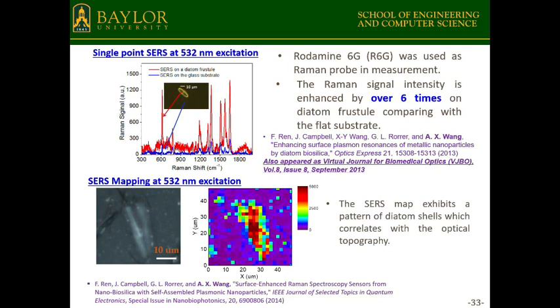And then we conducted SERS testing. So you can see the blue curve is the SERS from a nanoparticle on a flat glass substrate, and the red curve is the SERS signal from the diatom. The signal is greatly enhanced. In order to avoid random effects, we do a 2D mapping of the SERS over the entire region. So this is the optical imaging of the diatom, and this is the imaging of the SERS mapping. You can see these two are highly correlated to each other. It shows you the enhancement is not random. It's systematically from the diatom frustules.